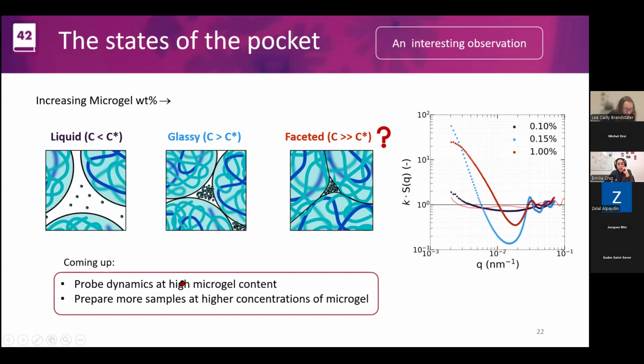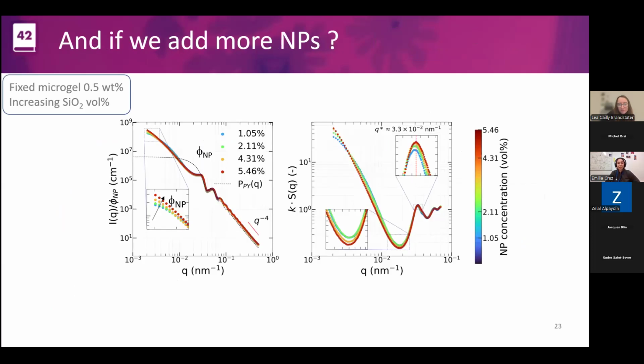And we will prepare more samples at higher concentration of microgels. So here you can already see that the particles reveal different states of the soft glass itself. So they're very good tracer candidates. What happens then if we add more nanoparticles? If we fix the microgel concentration like we did for the rheology experiments, and we increase more and more the nanoparticle content, we see that there's no dramatic shifts in the structures. It's pretty much the same story.